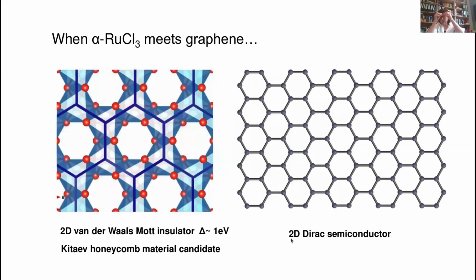So this is the idea: creating these heterostructures between alpha-ruthenium trichloride and graphene, especially because this can be done in the lab and has been done in the lab. So what happens when you bring these two systems together? Alpha-ruthenium trichloride is this layered van der Waals system, and this is your very nice 2D system, so in principle it should be easy to form these heterostructures.